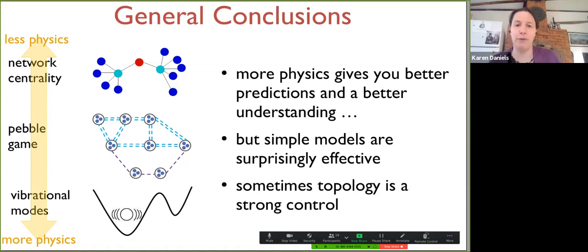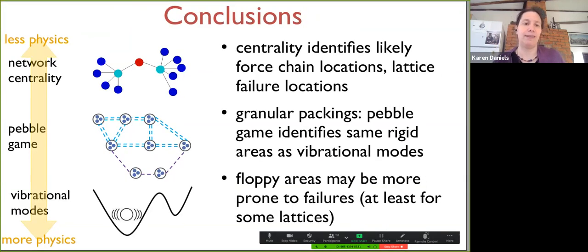All right, so some conclusions. I showed you a couple different viewpoints for looking at disordered materials, ranging from more physics to less physics. Obviously, more physics gives you better predictions and better understanding, but really simple models can be surprisingly effective. And we saw in several cases that just the topology was a very, very strong control on the system. And I think that's the big message. The more detailed message is that we're able to do all sorts of cool things like identifying where force chains are more or less likely to be, where failure locations are more or less likely to be, and that we can identify rigid regions through multiple methods that are in agreement with each other. And it's really promising that maybe some of the non-rigid areas, what we're calling floppy regions, may be more prone to failures, and at least for some lattices, maybe more generally than that.